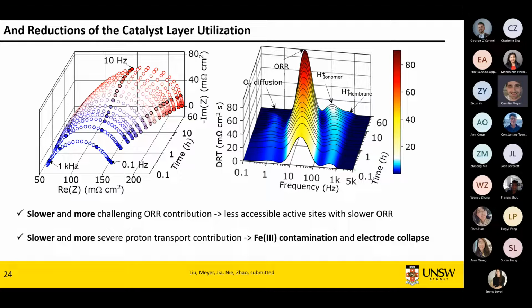The other problem you have is you have to remember the electrode is collapsing on itself. And so you initially had some very nice proton pathways through Nafion. Now your Nafion may be just not touching any catalyst anymore. A lot of it is not interacting with anything. And as a result, you basically have areas where it's extremely difficult to reach an active site.